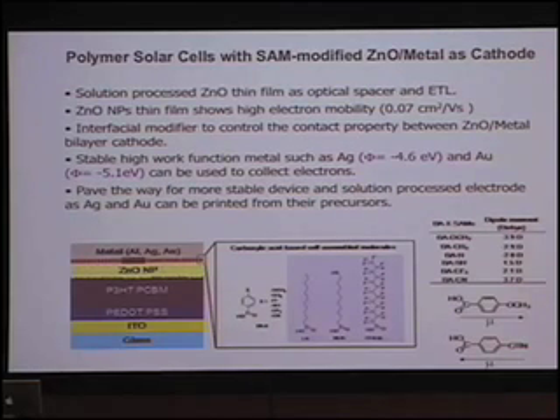First one is based on the conventional device structures, utilizing ITO as anode and also metal here as a cathode. On this polymer blend, we spin coated one layer of zinc oxide nanoparticles, and tried to grow some SAM on top of this zinc oxide. This SAM has 2 different categories. One is based on carboxylic acid with different kinds of either electron donating or electron withdrawing groups. With that, you can have different dipole moments, ranging from minus 3.9 debye to 3.7.